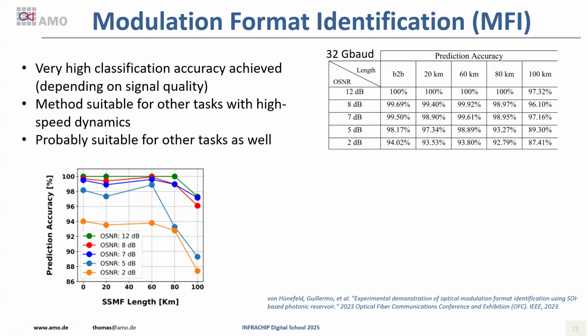According to our partners who did the experiment, they typically have it under 5 to 6 or 5 to 7 dB. 2 dB is like pushing the limits and seeing what this can do. And even at 100 kilometers, you can see this classification task that we did with this chip, and that too with a very highly lossy chip, was impressive. At first we thought there's something wrong, but we did it again and again.